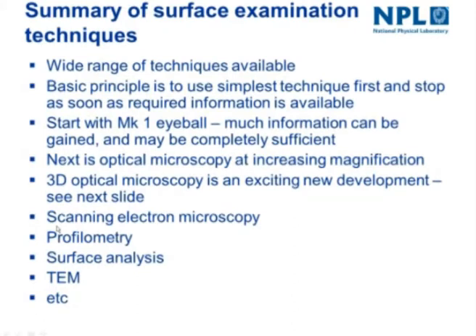So I mentioned that one of the important things you really ought to do is to use examination of the surface to check that the mechanisms that you're getting are sensible and match up with your application. There's a huge range of techniques nowadays. We're getting better and better at getting more and more information out about what's happened to surfaces. But there should be a basic principle here that you use the simplest technique first and stop as soon as you've got the required information. And just looking at your surface is the simple thing that everybody can do without any expensive kit, and it tells you a huge amount.